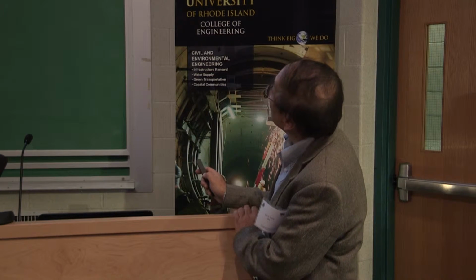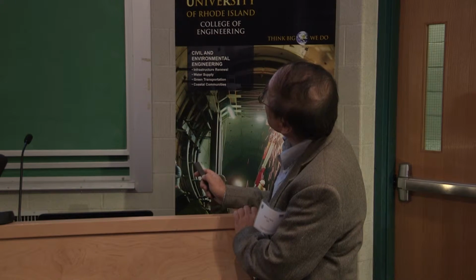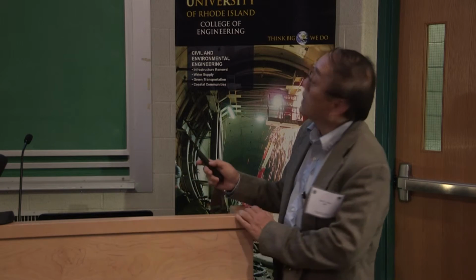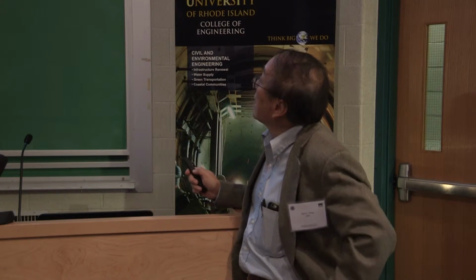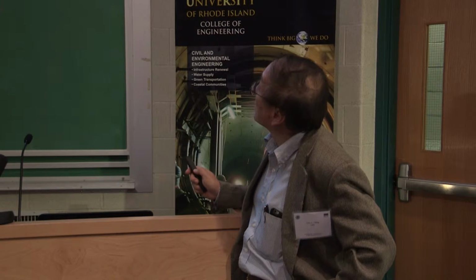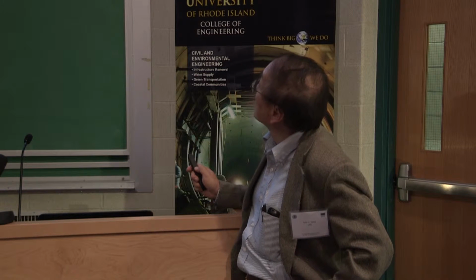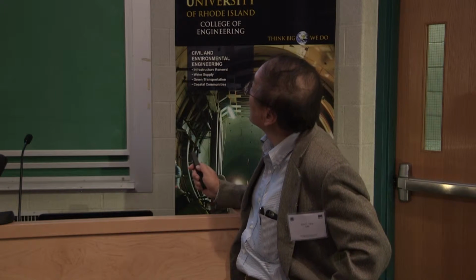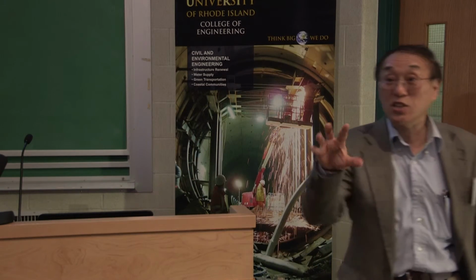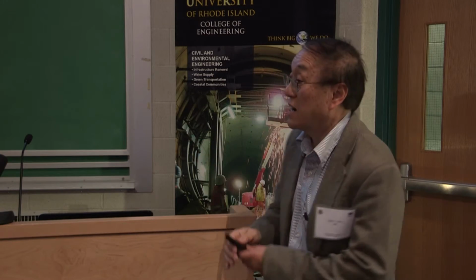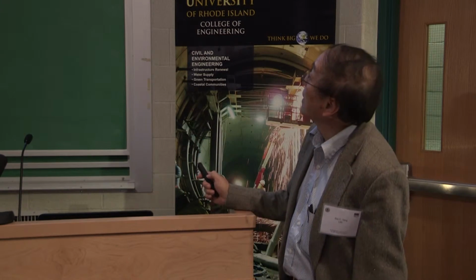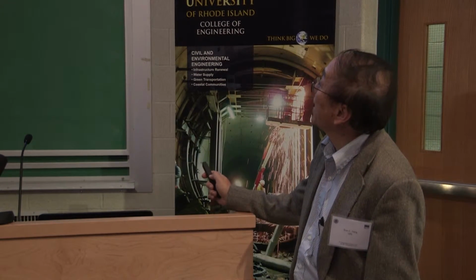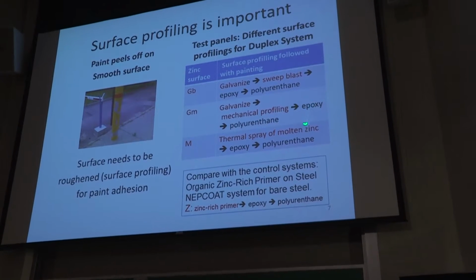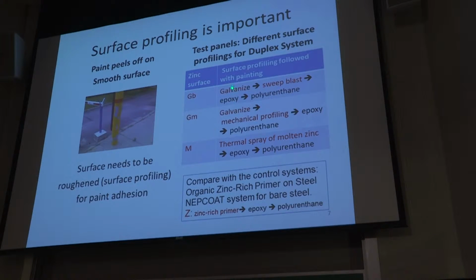That's one type of coating. Another type is less used, but has been advocated by a number of these galvanizers. They galvanize a smooth surface and then mechanically profile it. One method is using a grinder with a rougher wheel to score the surface so that there are channels on it, roughening the surface. So both take the galvanized surface, roughen it, and then apply the paint.